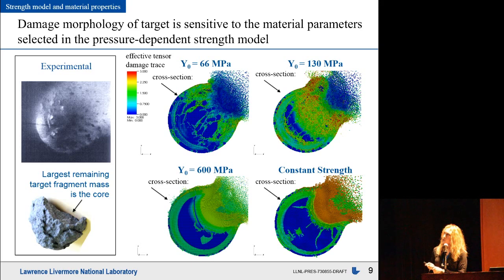For a low shear strength at 66 megapascal, you can see that damage propagates throughout the entire sphere, where again, the colors are the effective tensor damage trace, and we're looking into the cross-section of the sphere.